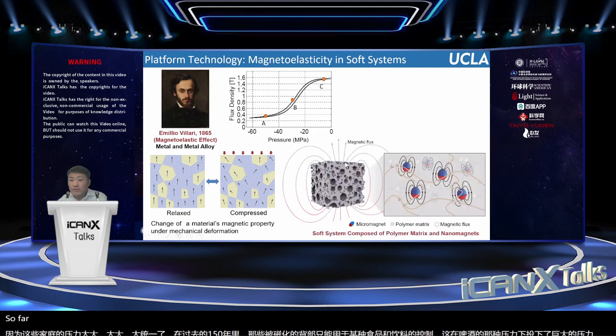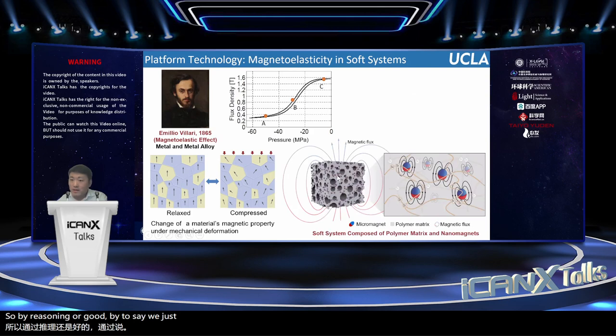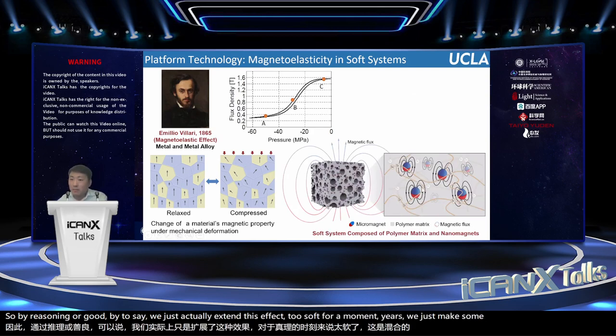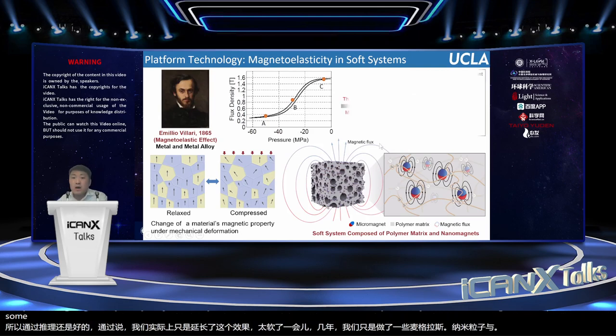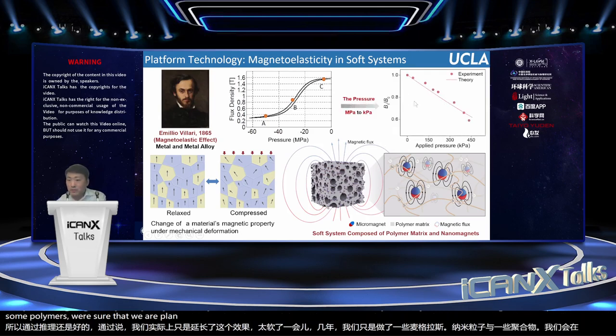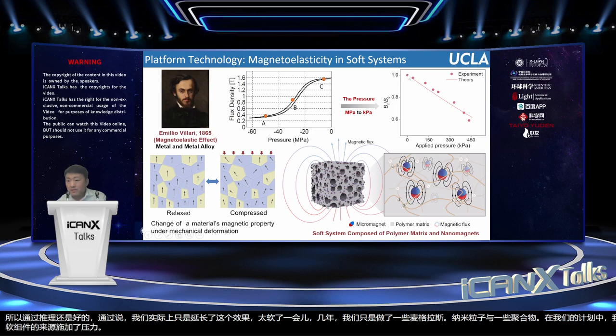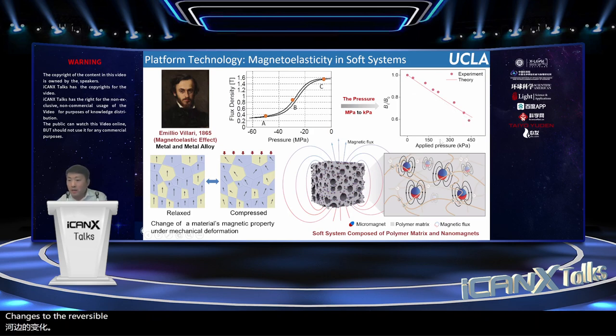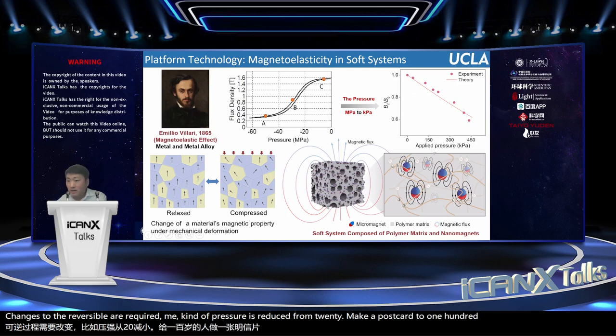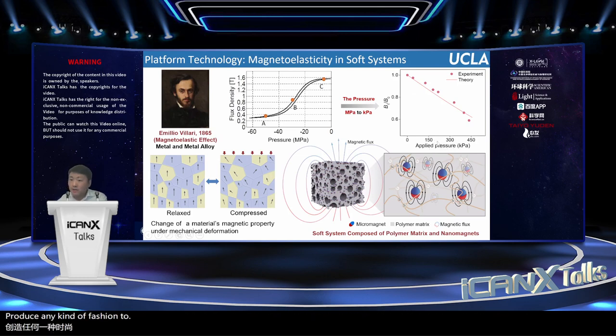So very recently in our group at UCLA, we extended this effect to soft polymer materials. We mixed some magnetic nanoparticles with some polymers. We show that when you apply mechanical pressure to such a soft composite, the magnetic flux density can also decrease, and this change is totally reversible, but the required mechanical pressure is reduced from 20 megapascal to 100 kilopascal. So this mechanical pressure is totally available from finger bending, heart beating, or other biomechanical activities.